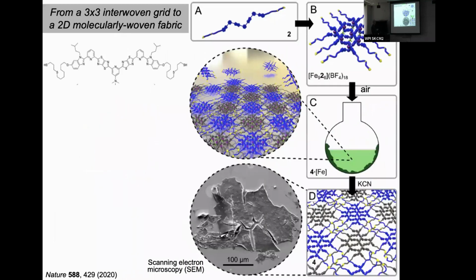So we took that ligand strand, we changed the end groups to have thiols on the end, because thiols can be connected together to form disulfide linkages by just the presence of oxygen, which can feed into a solid material. And we took the preformed grids and put them in solution, and they formed under an air atmosphere, which is going to oxidize. They formed films on the surface. We then treated it with cyanide to remove all the metal ions, so that we obtained a purely organic, no metal ions present at all now, so a purely organic polymeric material which had this flat, flaky structure.